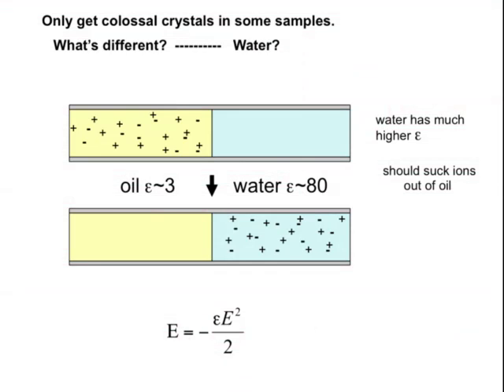Okay, and the problem is if the screening length is too small, then you won't get this long-range interaction, right? You die off exponentially. So what's obviously happening in this system is that the screening length was very large. The idea of what water would do is the following. The particles were suspended in an oil, cyclohexyl bromide, dodecane, things like that. It has a low dielectric constant.